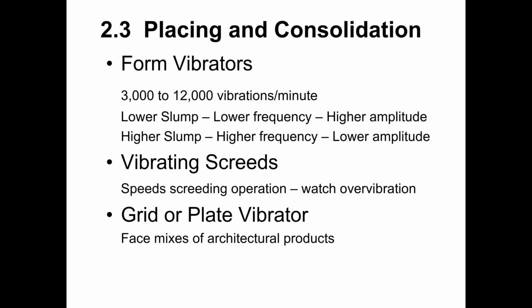Continuing placing and consolidation, form vibrators. Form vibrators come in a variety of vibration speeds or frequencies, usually anywhere from 3,000 to 12,000 vibrations per minute. Generally for a lower slump concrete, we want to have a lower frequency, higher amplitude vibration. For a higher slump mix, we want to have a higher frequency, lower amplitude vibration.